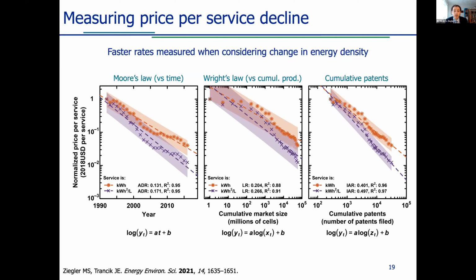And in orange here, I'm showing the results for all types of cells when we have a limited definition of service, just energy capacity. And in purple, I'm showing the results when we expand our definition of service to include energy capacity and energy density. And we see in all cases, we measure substantially higher rates of improvement. Our improvement versus time, our annual decrease ratio, increases from 13% to 17%. Our learning rate increases from 20% to just shy of 27%. So overall, we think these rates might be a more holistic estimate of how rapidly these technologies improved.